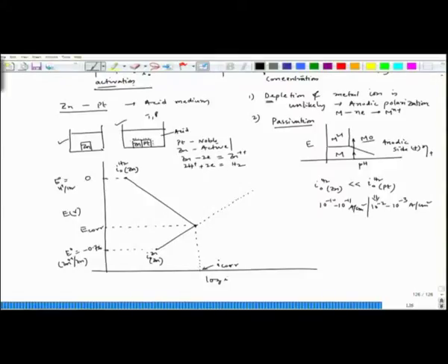Now if I consider hydrogen evolution on the platinum surface, its exchange current density is pretty high at this point. So this is I0 hydrogen on platinum surface, and E0 of course would be the same, 0, because we are considering hydrogen evolution, and then it would also have its own cathodic polarization, and it is cutting here. Now the question is, would this be my new mixed potential?